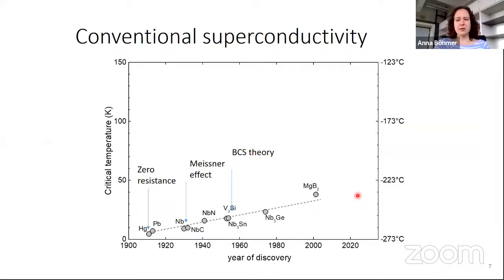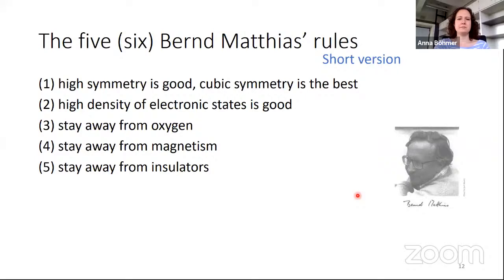Over this period, and with all of these materials in mind, a couple of rules have been established for how to find a good, high temperature superconductor. And they are the famous Matthias rules. So in a short version, they say, try to look for superconductivity in a high symmetry material, ideally a cubic material that's the same along all directions. High electronic density of states also helps. So lots of states for electrons at the Fermi surface. Materials that contain oxygen are not a good idea. Materials that are magnetic are not a good idea. Insulators are not a good idea.